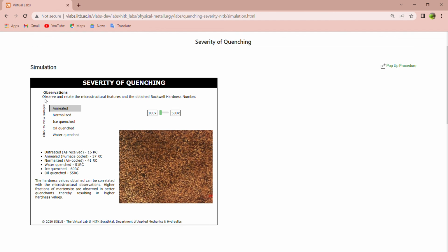The observation. Observe and relate the microstructure features and the obtained Rockwell hardness number. Untreated 15 HRC, annealed 37 HRC, normalized 41 HRC, water quench 51 HRC, ice quench 60 HRC, the highest number, and oil quench is 55 HRC. The hardness value obtained can be correlated with the microstructure observation. Higher fractions of martensite are observed in better quenches, thereby resulting in higher hardness values.